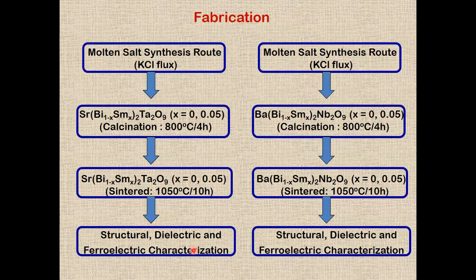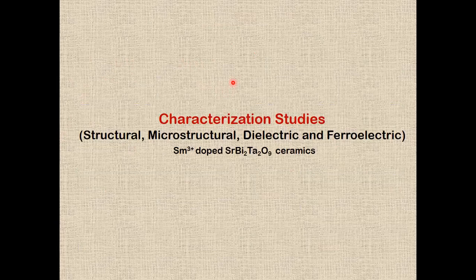I have fabricated samarium-doped strontium bismuth tantalate and samarium-doped barium bismuth niobate ceramics using a low-temperature molten salt synthesis route in which KCl was used as a flux. After preparing these compounds, they were subjected to various physical property studies including dielectric and ferroelectric characterization. I will now discuss the structural, microstructural, dielectric, and ferroelectric properties of samarium-doped strontium bismuth tantalate ceramics.